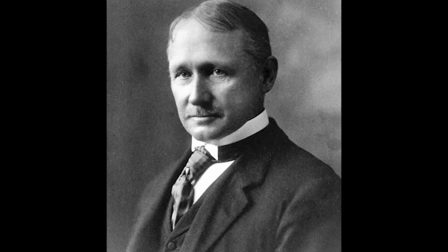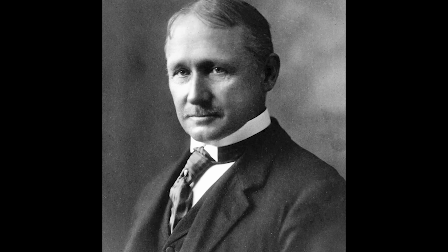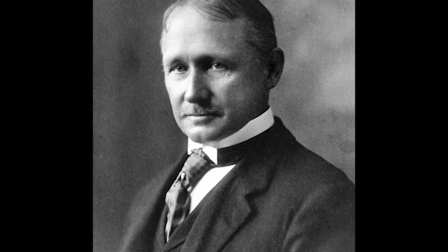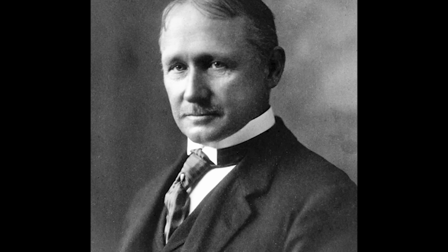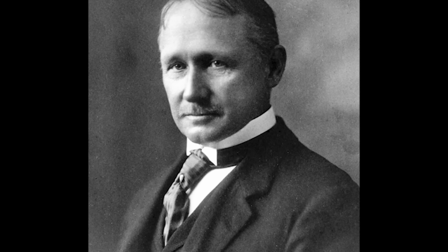Through the fall of 1900, he and White systematically identified the precise conditions where their steel excelled and where it failed catastrophically. The breakthrough was not brittleness resistance, they realized, but heat resistance. The tool was not meant to replace all cutting applications, but to revolutionize operations where heat buildup had always been the limiting factor. Working with Norwegian mathematician Carl Barth, Taylor developed operating guidelines that transformed high-speed steel from dangerous experimentation into controlled technology. Continuous cuts at sustained high speed, rigid machine setups that eliminated vibration, specific feed rates that maintained constant tool engagement with the workpiece. Most importantly, they determined that Taylor-White steel excelled where conventional tools failed from heat buildup, not where shock resistance was paramount.